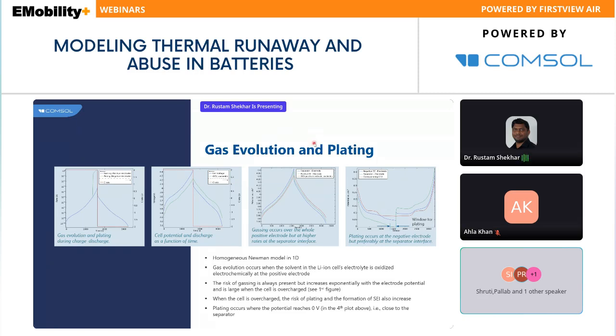So in these failure mechanisms, we can see gas evolution at the positive electrode and lithium plating at the negative electrode. When both work in parallel, along with that you can see the SEI formation also. So we have lithium plating, SEI formation, and gas evolution, everything happening all together. This homogeneous Newman's model in 1D can be modeled, and we can see the risk of gassing and